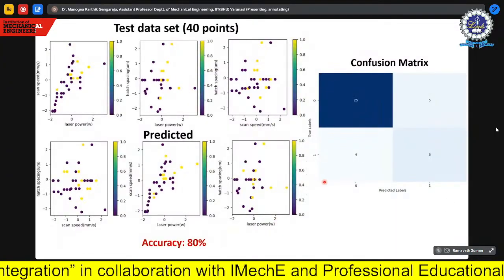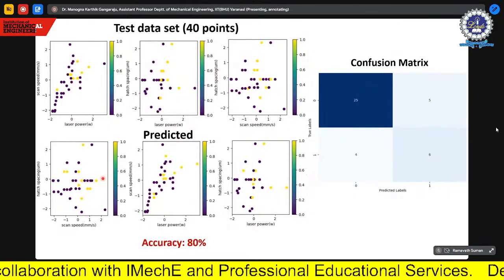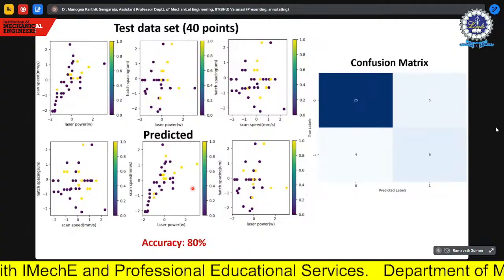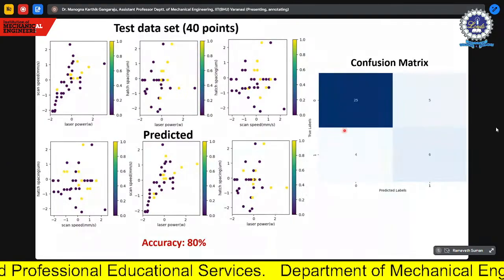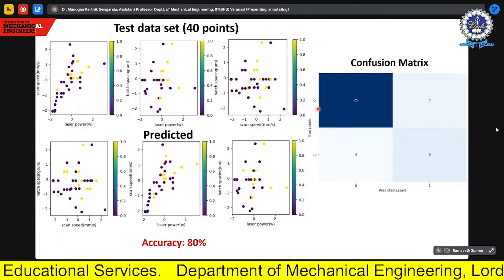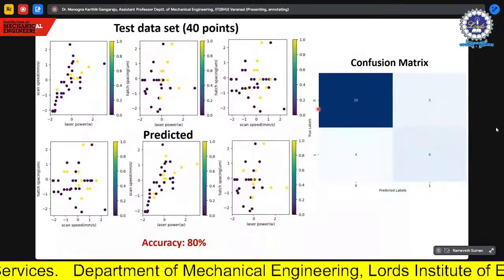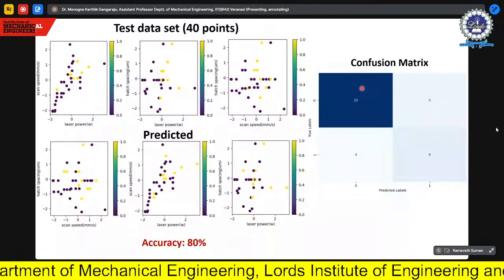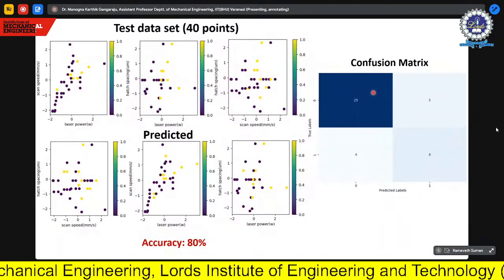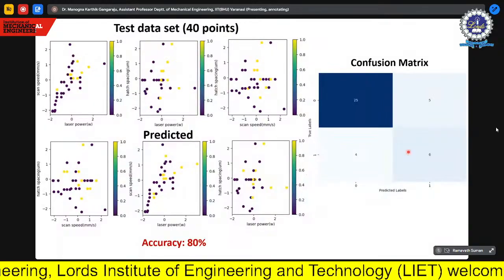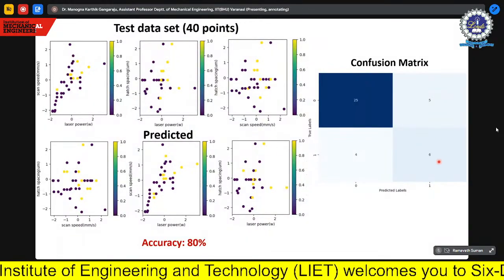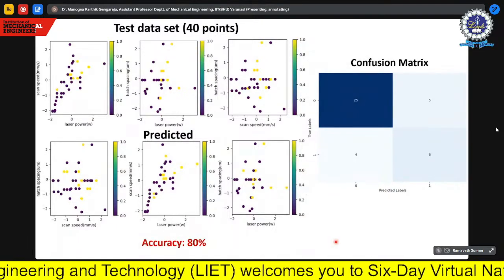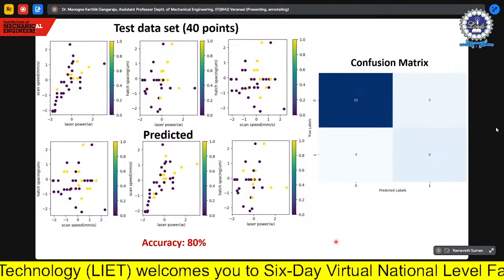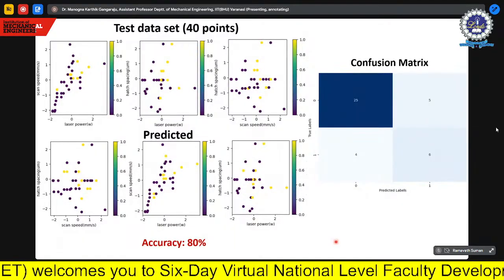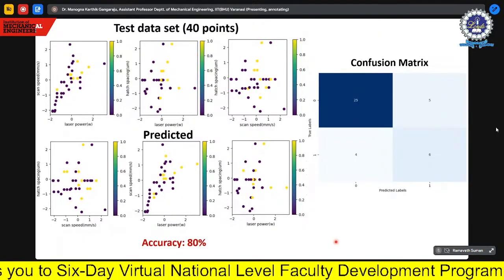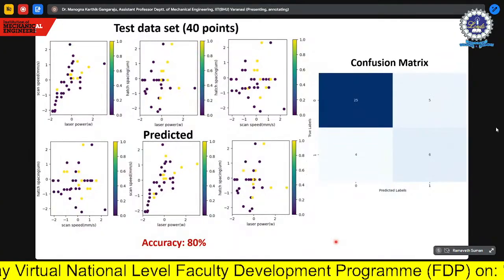Then if you see, this is our test data and this is our predicted data, and we are having close to 80% accuracy. So basically what we are trying to say is, if zero is the sample without any defects, 25 times my algorithm is predicting correctly and 5 times it is not predicting correctly. In the same way, when one is the defect region, 6 times it is predicting correctly, 4 times it is not predicting correctly. So this is the problem. We can solve this problem only if we have a large data set. When my data set is very large, I can improve this algorithm further so that my accuracy improves further.